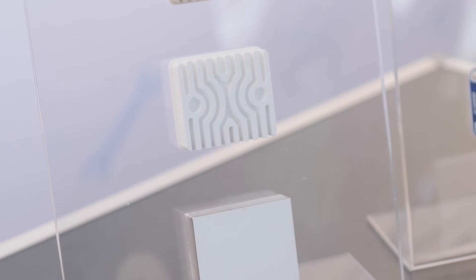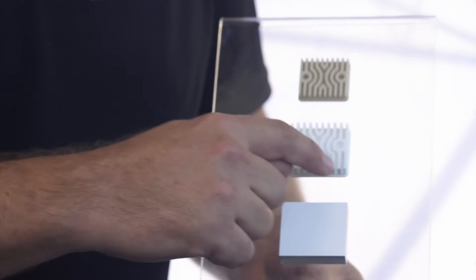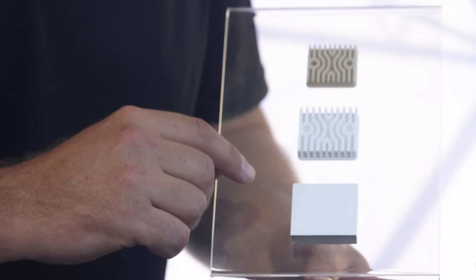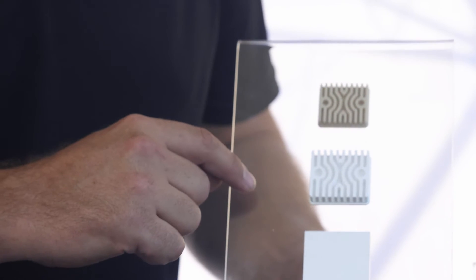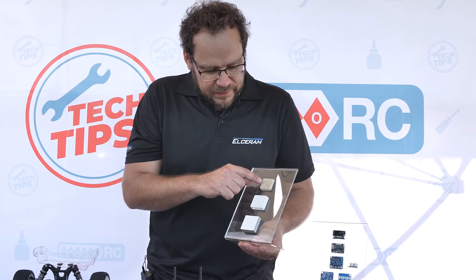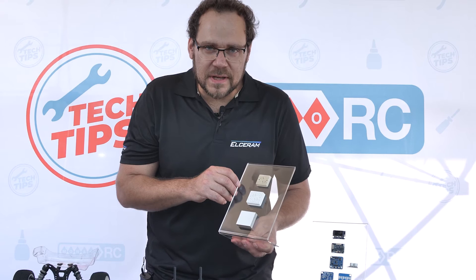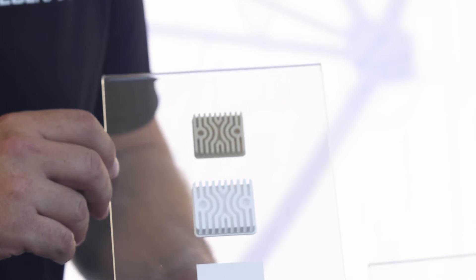During cooler production we are using dry pressing technology, so from the aluminum nitride powder this part is pressed using 30 tons. After that we use a milling machine for shaping, and here you can see the cooler after the sintering process at a temperature above 1800 degrees.